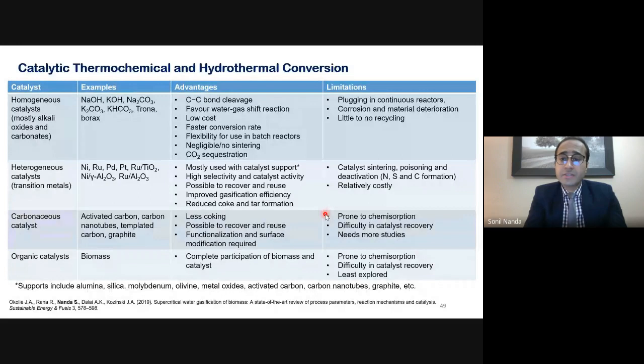But the limitations are catalyst sintering, poisoning, and deactivation because of the formation of heteroatoms on the surface, which tend to block the pores of the porous catalyst support. And also, these transition metals like nickel, ruthenium, and palladium are generally on the expensive side. So using heterogeneous catalysts could be slightly expensive from an industrial perspective.